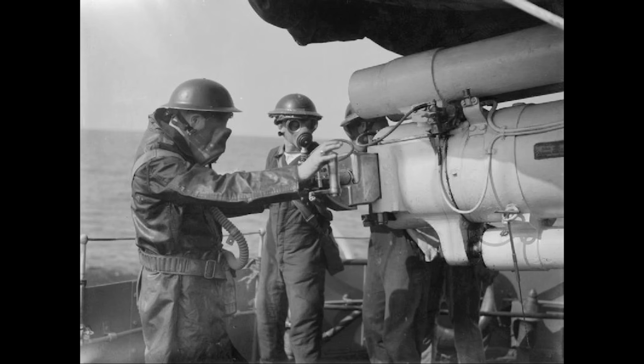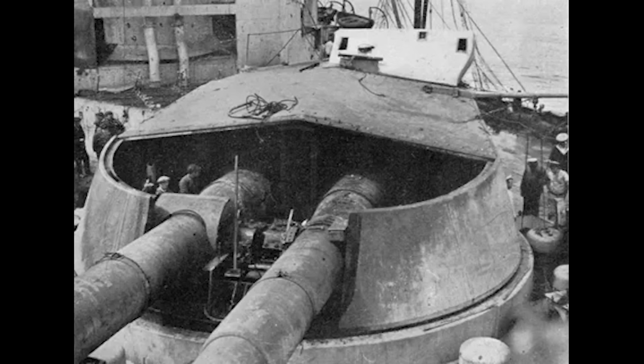American armor manufacturers were solving the wrong problem, and they were solving it so effectively that they created a new problem nobody recognized. They were optimizing armor to pass Criterion 3, cause serious projectile nose damage. They were making armor that would visibly damage test projectiles during acceptance trials, ensuring the armor would be accepted by Bureau of Ordnance inspectors. What they were actually doing, though nobody fully understood it until after World War II, was making armor more likely to fail by exactly the mechanism that had destroyed the Midvale non-cemented armor back in 1921.